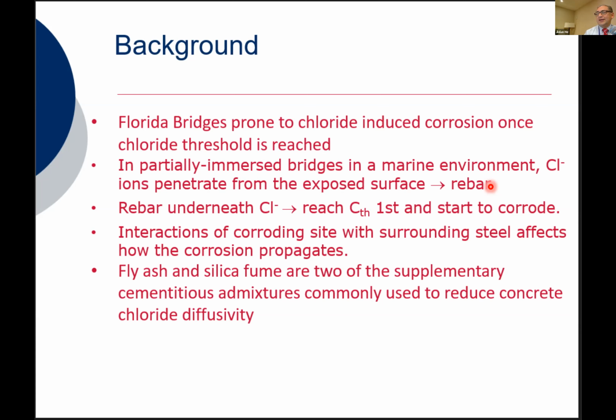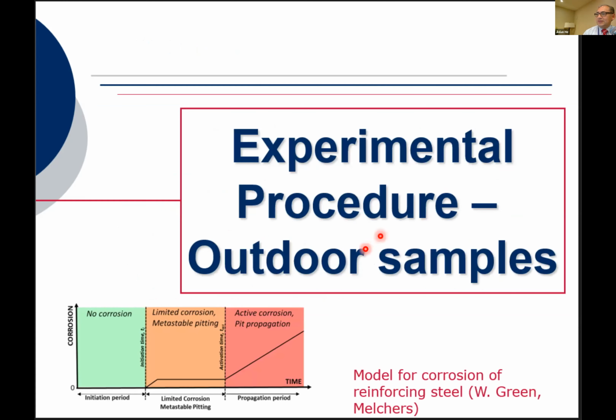Pierre already mentioned that typically in a partially immersed structure, the chlorides need to penetrate and reach the rebar, and several speakers mentioned yesterday, this is your typical time to corrosion initiation. But what I would like to introduce here is that more recently, some researchers like Melchers in Australia, as well as Mr. Green, who is also in Australia, have proposed that right after the time to initiation, you can likely observe metastable pitting as well as limited corrosion taking place. Eventually, the corrosion becomes more persistent, and that is the region they are now calling active corrosion. And we have observed some of that in the samples that I'm going to be describing here today.